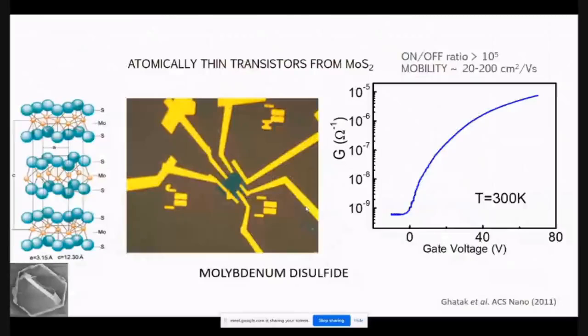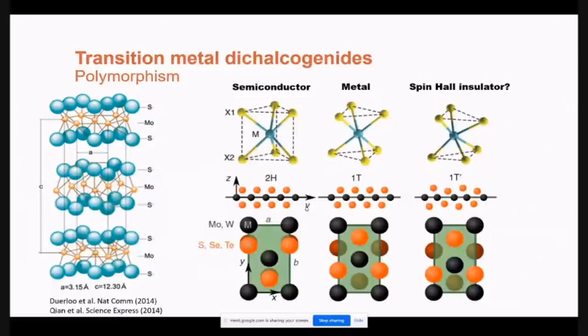Okay. But in the case of molybdenum disulfide, we have not just a very interesting field effect transistor property, but they also have very interesting structural polymorphism. The standard naturally occurring semiconductor is of 2H type. But what happens if I essentially shift one of the layers on top by one layer? This becomes a metal. From a semiconductor, the naturally occurring 2H structure, it becomes a metal. But it turns out that this 1T metallic structure is not really stable, and the lattice distorts because of some soft phonon modes, and it becomes what you call a 1T prime, or the distorted octahedral structure, and that turns out to be a spin Hall insulator.